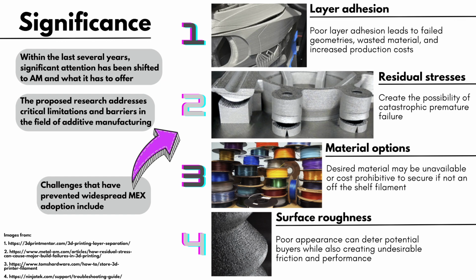Some of these critical issues, which are shown on the right, include poor layer adhesion, where poor bonding between layers leads to unsuccessful prints, wasted resources, and increased production times. Residual stresses, which typically lead to premature failure in manufactured components. Availability of material options, as a preferred material may not be readily available off the shelf, leading to the need to create a custom filament with high costs. And surface roughness issues. If a print doesn't look good, it may not be viable for end use, and a poor surface finish could also create undesirable friction while in use, also causing premature failure.